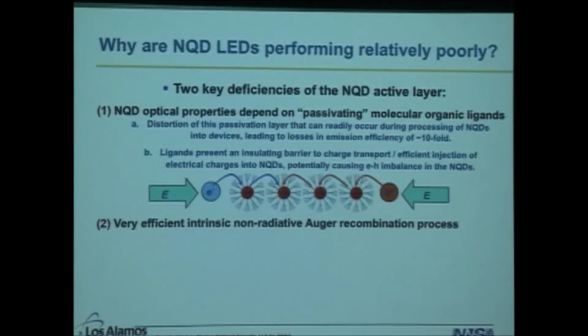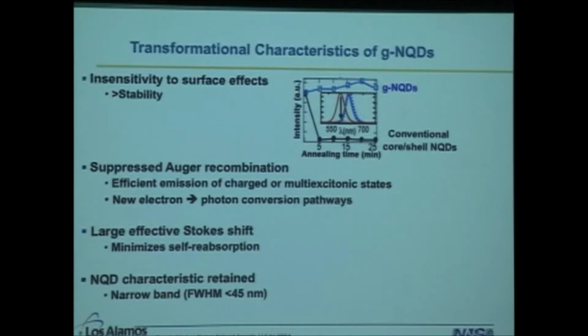In addition, these ligands can provide an insulating barrier to charge transport. If you want to build a device that has multiple layers of quantum dots, then you're dealing not just with the emitting core, but with this insulating organic material. You may also affect the different carriers differently and create an electron-hole imbalance in the quantum dot. So ligands are generally considered bad for LED applications. In addition, we've already talked about the Auger recombination process. In LEDs, the emitting material can become charged, and by Auger processes a quantum dot will then become dark. So those are the two deficiencies of a conventional quantum dot system.